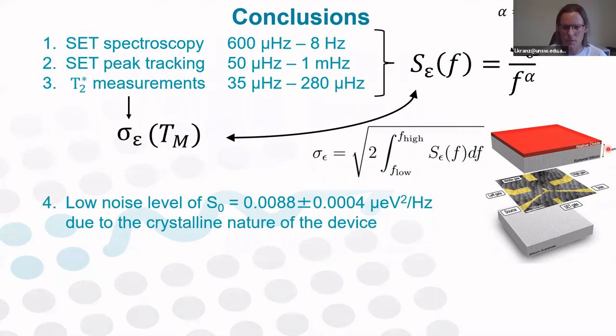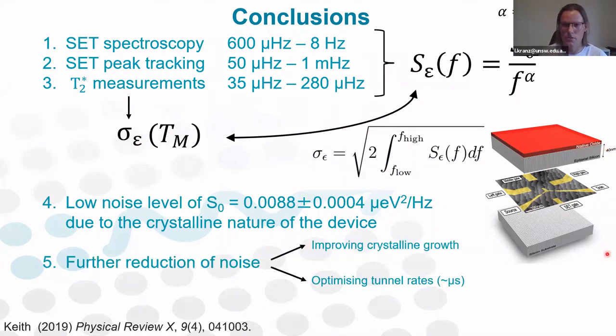So going forwards, we definitely want to further improve the charge noise characteristics in our devices. We think there's at least two ways in which we can do it. First of all, we can improve the single crystal in our device. This encapsulation layer above our device is something we grow ourselves in a growth chamber, and we think that we can further optimize this growth to have even fewer two-level fluctuators in this layer.